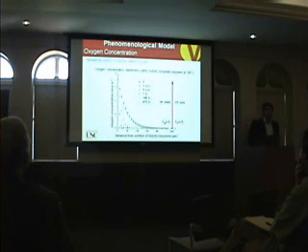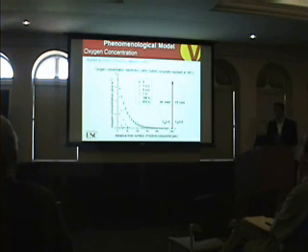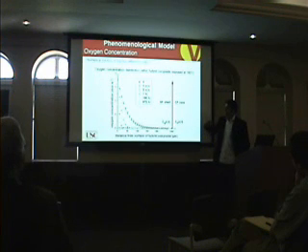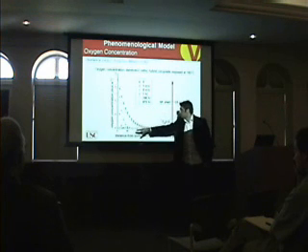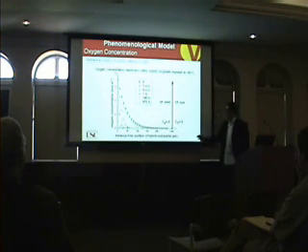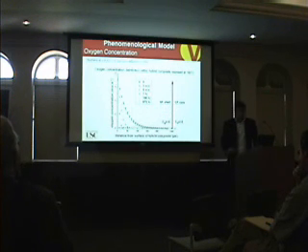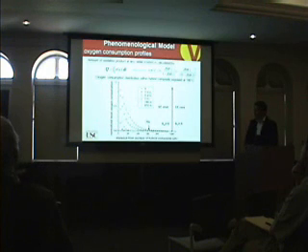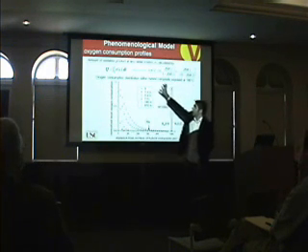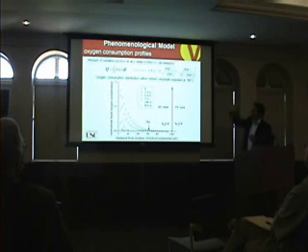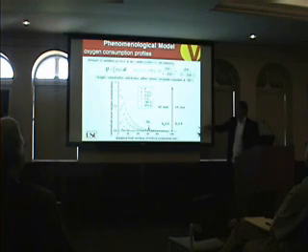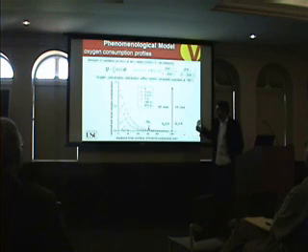Then we used the MATLAB software, and we had two partial differential equations. Those are coupled with each other, and by solving and plugging those parameters in, you're going to see that this is the surface of our material, and when you go further in, you see the distribution of oxygen, and the distribution decreases over the depth of your material. And if you consider the oxidation terms, we want to know at each position how much product of oxidation we have. So we integrate from 0 to time t, and we measure the oxidation product.